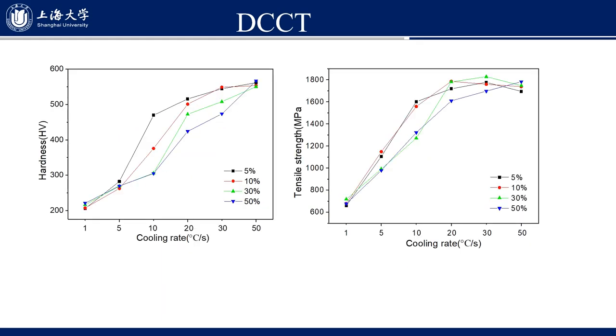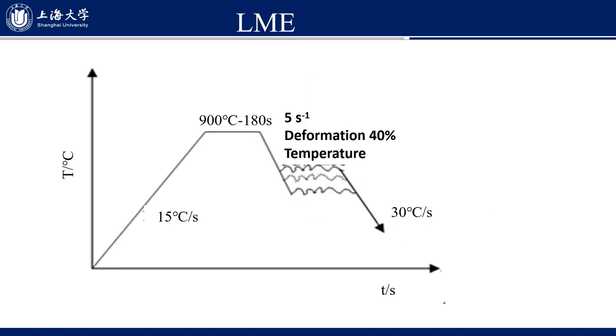This slide shows the hardness and tensile test result. It is clear that the hardness for certain conditions reaches a very high level, and tensile strength reaches around 1.8 gigapascal. This slide shows the liquid metal embrittlement research.